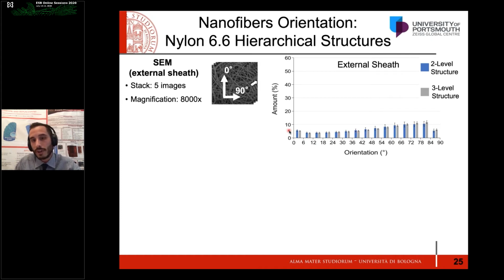You can see that the nanofibers are basically randomly arranged, but with a slightly circumferential orientation of the nanofibers on the membrane, confirming what I said before about the possibility to tune the orientation of the nanofibers on the membrane.